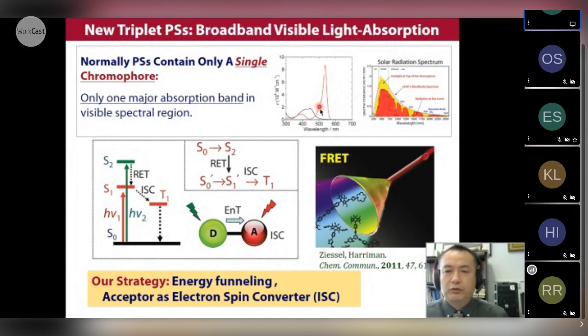solar light. But for normal photosensitizers, we have only one chromophore in the molecular structure, and we have only one major absorption band. That is not good for application. I think the answer to this problem is we can prepare a photosensitizer containing energy donor and energy acceptor. Both parts give absorption, but at different wavelengths. It's similar to the FRET molecules. So in the normal FRET molecules, we have energy donor and energy acceptor. They give different absorption. And then we have the emission from energy acceptor.